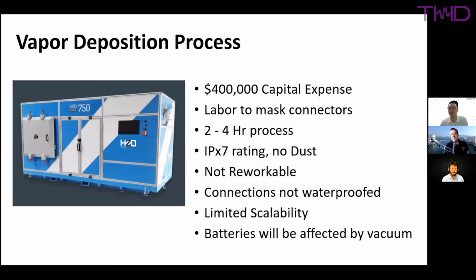Yeah. So this was new technology. People saw something that was new and innovative and thought that maybe this would be a good idea. Mm-hmm. But again, the coating's so thin, right? You're at 100 nanometers to about 200 nanometers, and that's doing multiple layers of coating. So because the coating's so thin, you don't even get a dust rating on there. And with our coating, we're about 500 nanometers to about 1 micron. And you do kind of require that coating thickness for durability.